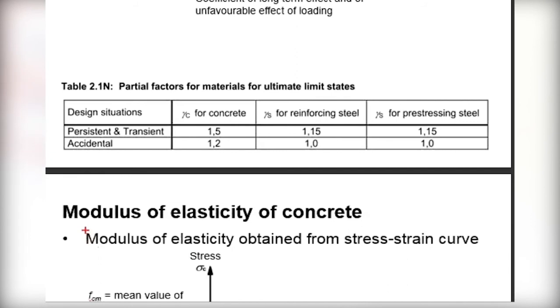Now as per the clause, from table 2.1 of the Eurocode, the value of the partial safety factor for the concrete at the transient is about 1.5, while for the accidental it is about 1.2. For the steel, the partial factor at transient is 1.15, while the accidental is about 1.0, the same as for pre-stressed and in other natures. This is how you can take your partial safety factor according to table 2.1 of the Eurocode.